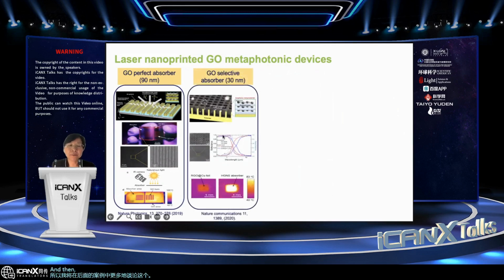And then on the other hand, so we want to further reduce the thickness of graphene because graphene, it's still like nanomaterials. People may worry about the cost. Therefore, we want to reduce the thickness as much as possible and also introduce ultra high absorption. So in that case, we have like a trench structure at the bottom, which is made by copper. And then on top of that, we have a layer of graphene, which is only 30 nanometer. And then this structure basically allow the control of the response of the sunlight, and then to match the sunlight absorption. And then the absorption is actually happening at the graphene layer. So using this two design, the entire solar spectrum can be absorbed and converted into heat.